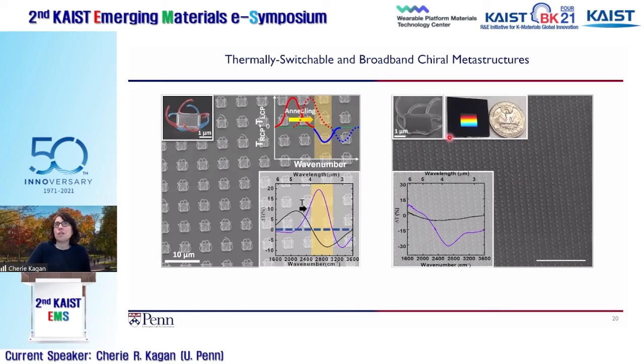And then we also showed, for example, you could make many arms. You could pattern different lengths, and they would each contribute their resonances at different energies. You could make these start to work as broader band chiral materials. And so we are trying to widen the spectral range over which it operates. And this is just showing you how we could make these over large areas using this fabrication process.